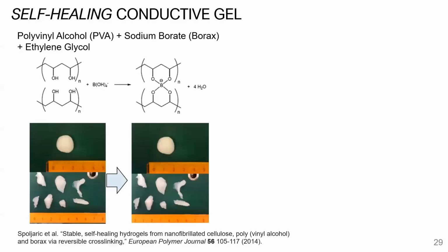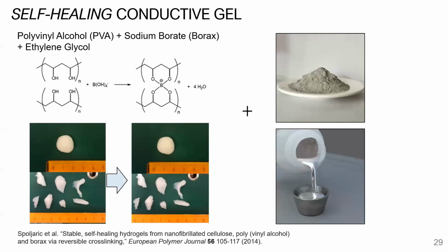And so as with natural tissue, we want to have this self-healing capability. Thankfully, when it comes to gels, there's been a tremendous amount of work by groups who have looked at the self-healing properties of these gels. We are simply adapting what's been known for over a decade about these material systems. Particularly, we adopted a composition of borax, PVA, and ethylene glycol as a solvent, and then we blend in the liquid metal and the silver.